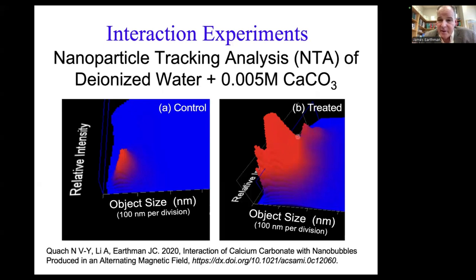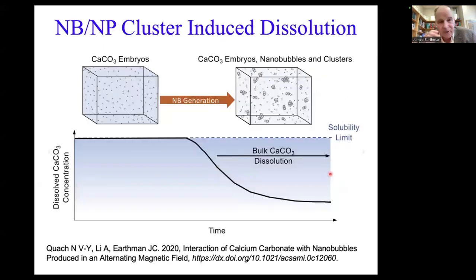The nanobubbles are probably this peak here, the low peak. And then we have this big peak in the middle that goes out to larger sizes. We believe those are the clusters. Those are clusters of nanobubbles and nanoparticles together. And they go out to much larger sizes. It's hard to see on this image, but they do go out to larger sizes. So here's the theory for the interaction of nanobubbles and nanoparticles.